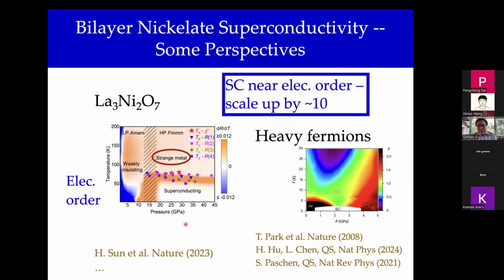So coming back to this overall set of materials, let me just put some perspective and a bit of my bias into this. When I first heard of the report of superconductivity in the bilayer at such high pressure, I remember talking to a number of people, in particular with Chandra Varma, and we took the normal state resistivity and extrapolated that to zero temperature, and we found that the extrapolated value is only 4 times the measured low temperature resistivity. So one could have put in some skepticism of the initial result, but as I mentioned, that has been sorted out. Zero resistivity certainly has been achieved through the work of Zhejiang University and IOP.